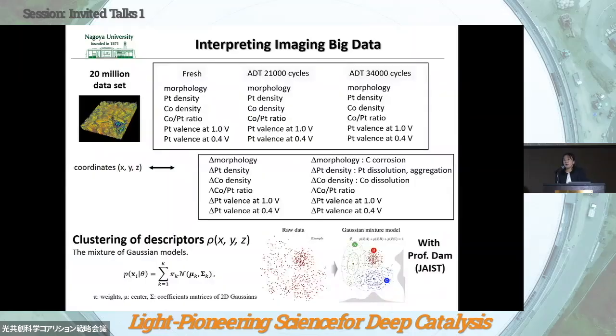So imaging data is a huge data set. We have a 20 million data set from one measurement. And we can obtain many different parameters by the analysis of the combination of the imaging and the spectroscopy. For example, the morphology or amount of the elements, and valence state or coordination structure, and we can calculate the difference of these parameters, which is related to the degradation of the catalyst. So how do we understand this kind of data set in chemistry?